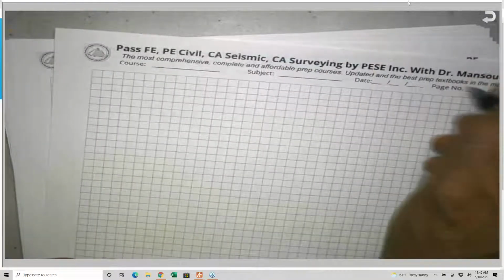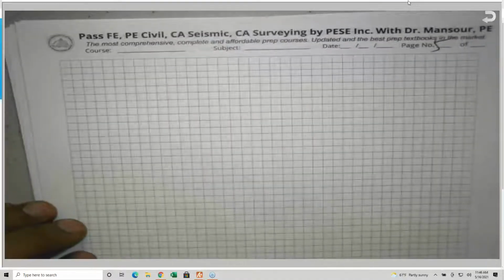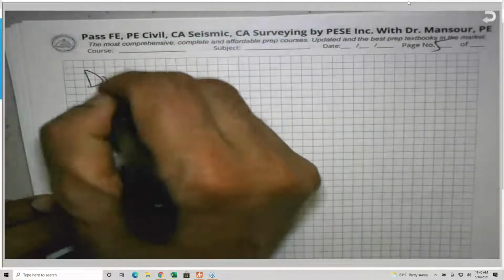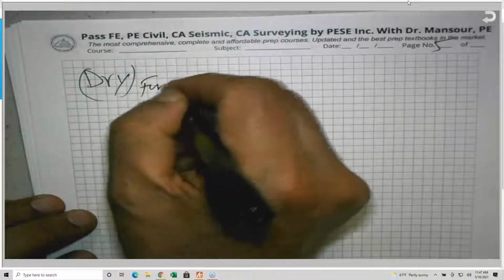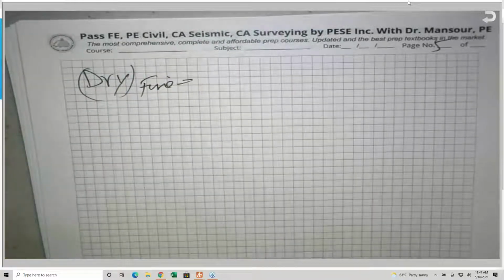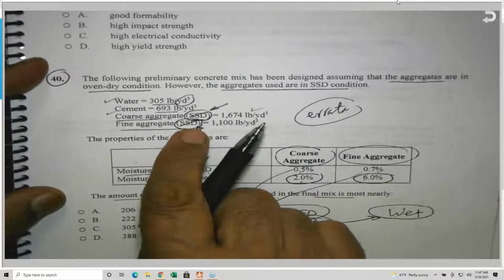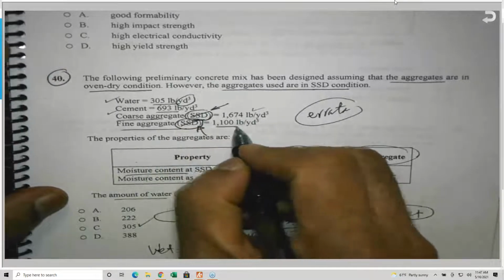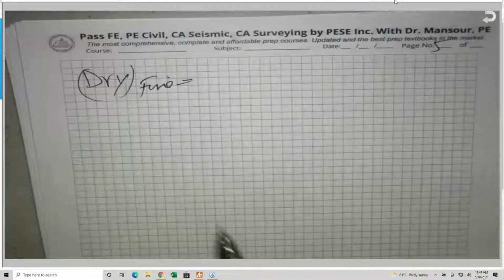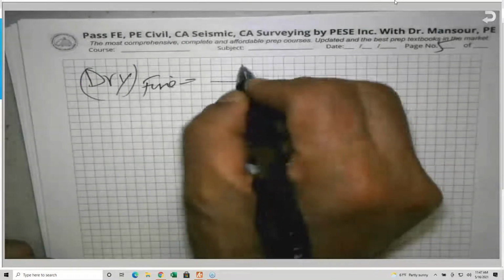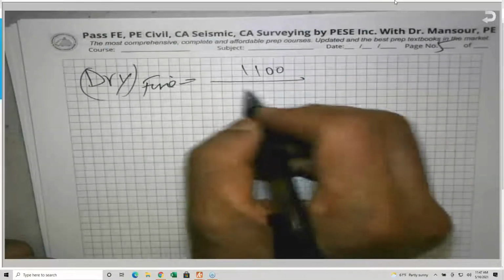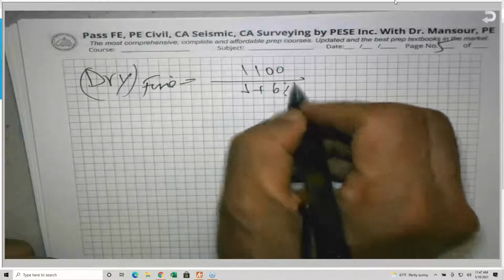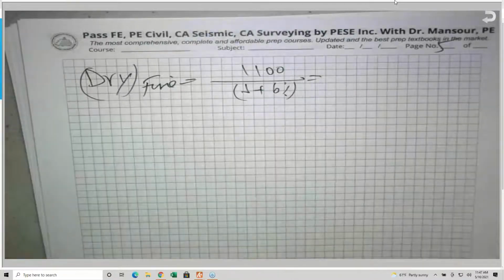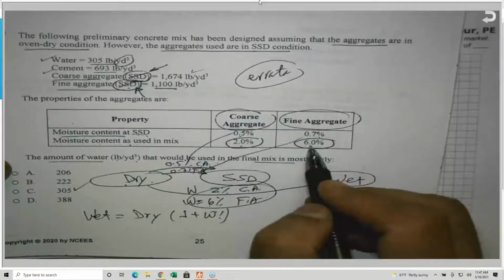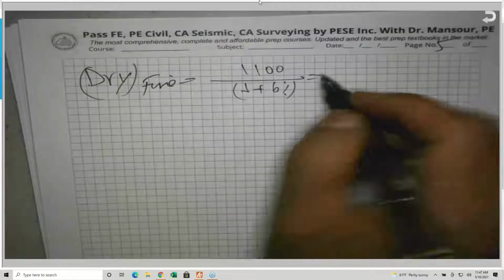I will do the same thing for the fine, and this will conclude the problem. So it is the dry weight for the fine. He said that he put in the fine how much? He put for the fine 1100 pounds. And again, the SSD, it shouldn't be here. And after I finish, I see my solution. 1100 pounds divided by 1 plus 6%. Who said 6%? Here it is. The fine, 6% moisture. So I bring this to the dry state.